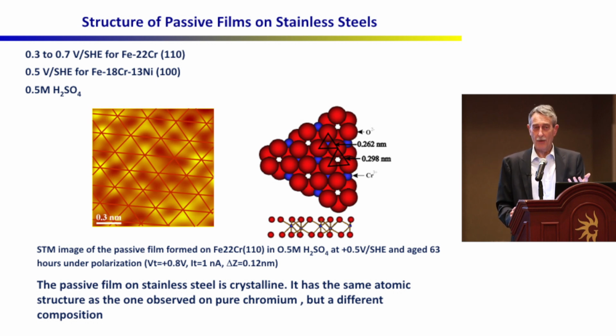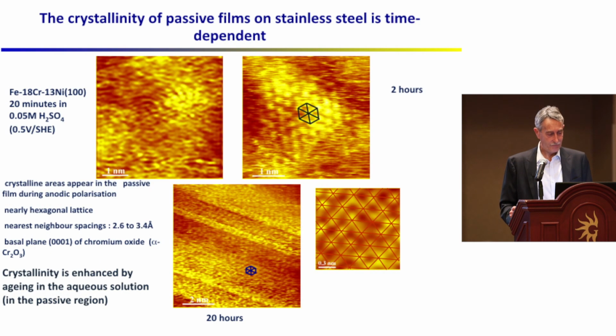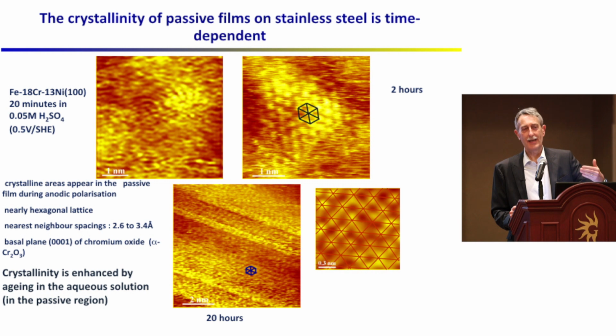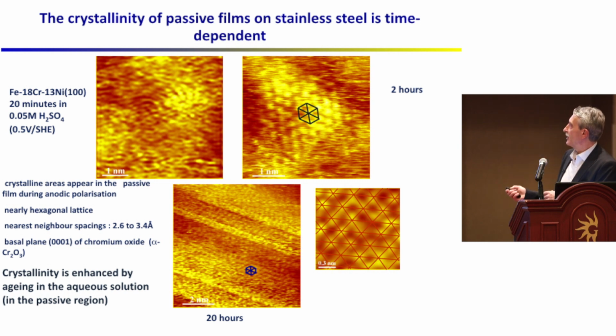So the stability of these layers is entirely related not only to the chemical nature, but also to the structure. So for a given oxide, the structure is the determining feature for the stability. Okay, now we looked at the effect of potential and time, and we saw that if you take an alloy, crystallinity is not instantaneous. It takes time for the passive layer to become crystalline, and we could see that by looking at different passivation times.